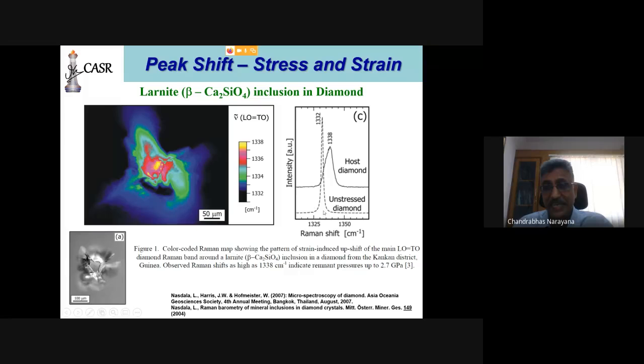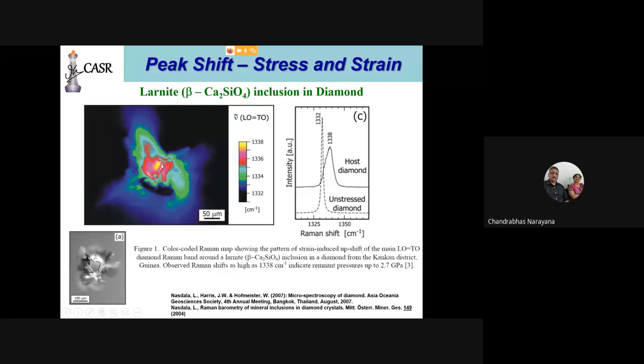And what is the pressure required? It is about 2.7 gigapascal, which is equal to 27,000 atmospheres. So you can see the pressure on the diamond here is around 27,000 atmospheres. So you can see an inclusion of calcium silicate is much weaker compared to the diamond, but just because it is included here, it creates stresses. And the moment it creates stresses, the molecular or the material properties would change.